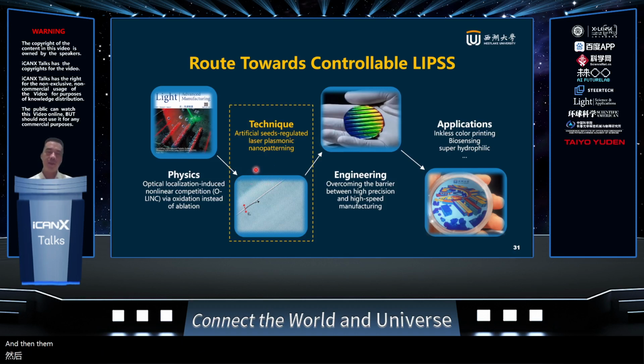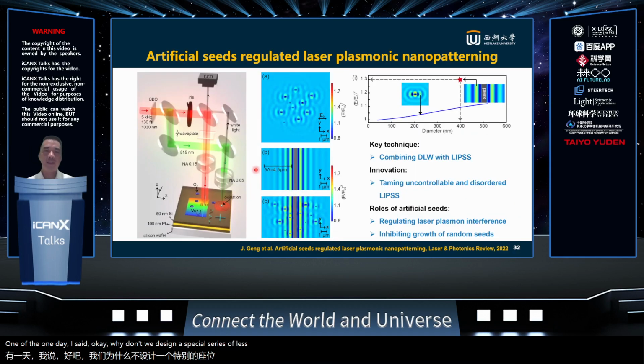And then one day I said, okay, why don't we design special seeds? This is one of the very recent publications that will appear in Photonics Review shortly. We use two lasers in this case. Instead of only a femtosecond laser with these parameters, 5 kilohertz repetition, 330 femtoseconds, 1030 nanometers, we also have another, half wavelength, based on nonlinear effects. We also generate a shorter wavelength, 515 nanometers.